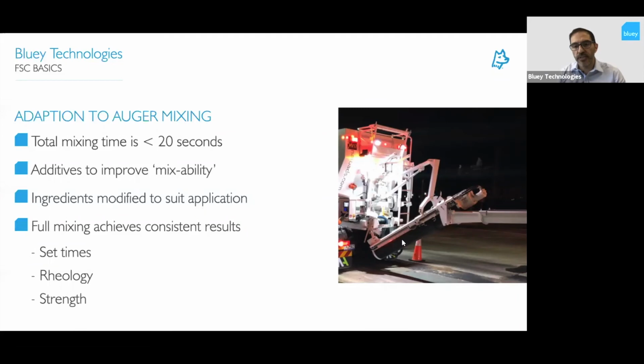Now you can see in that photo the little black section there, which I'll point to with my arrow, this section here. This is an auger in here, and the powder and the water all gets delivered into that bottom point there, and then it gets shuffled up this chute, and as it's getting shuffled up by the auger, it's also mixing at the same time. But it only allows around 20 seconds of mixing time.